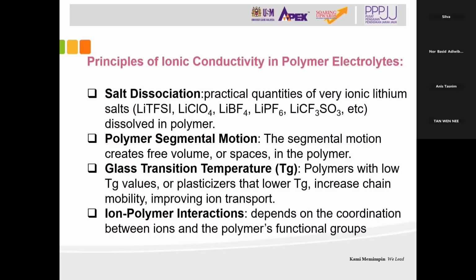Another one is the glass transition temperature. All of us know that the glass transition temperature of the polymer will affect its flexibility. Polymers above their Tg are more flexible and allow greater segmental motion, and it will result in higher ionic conductivity. Polymers with low Tg values, or plasticizers that lower Tg, increase the chain mobility and will improve the ion transport.